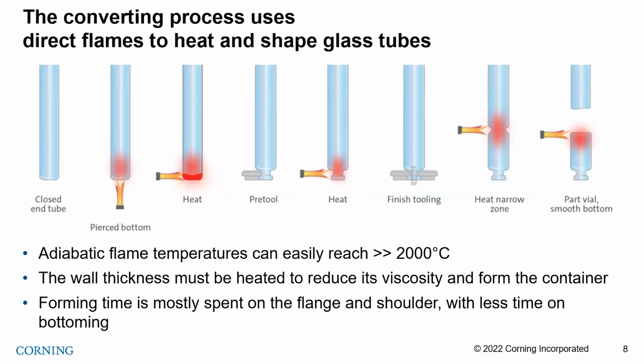And so this just shows you during that tube to vial converting process, the glass is heated and cooled and heated and cooled several times, giving many opportunities for that evaporation and condensation process to occur. And as a result, the surface chemistry on the inside of that glass that would eventually be put in contact with the drug product is significantly different from where we started.